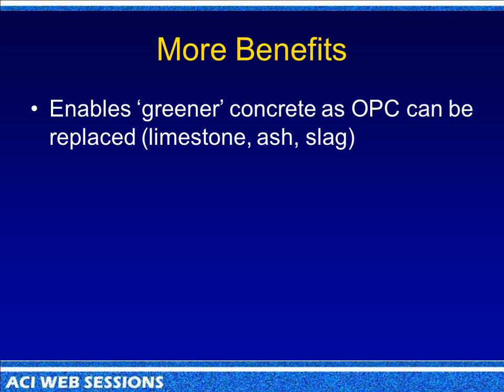You can actually get greener concrete because, like everybody wants to do, is more fly ash. Well, let me tell you, the chemical shrinkage of fly ash is twice that of cement, and the chemical shrinkage of slag is 4 times that of cement. So you got to get the water. Judy was talking about how dense these mixes are. You can't get the water in to cure them.